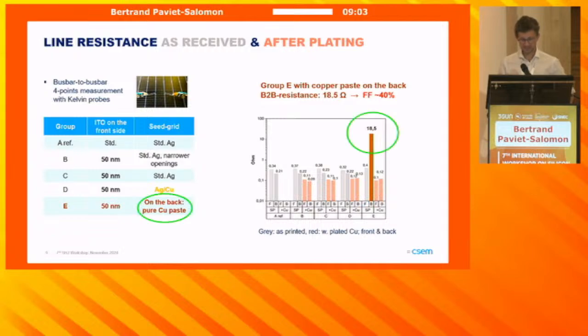Maybe of interest are the results of group E. Those feature at the back a pure copper paste, and as such, as received before plating, they feature a pretty high line resistance, which would limit the fill factor of devices made thereon to roughly 40%. But as you can see, once we do the overplating on those, the line resistance falls back again to values very similar to what you could obtain with pure silver or SCCP paste. And I will actually come back to this point a bit later on.